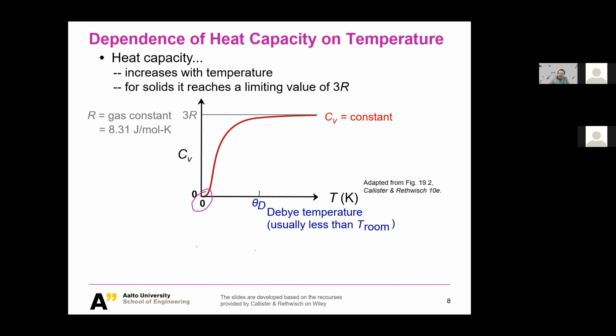And basically, when you increase your temperature, the specific heat capacity will increase. And when a threshold is met, this is the so-called Debye temperature. This is a temperature which is usually less than room temperature, so close and less, not higher than room temperature. And the specific heat capacity will tend to go to a constant. So especially the CV will tend to go to a constant, not the CP. And this constant is equal to 3R.